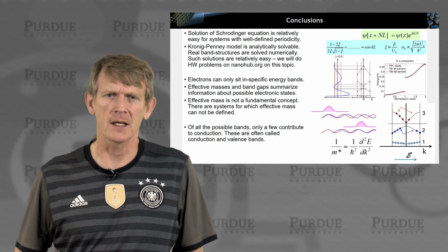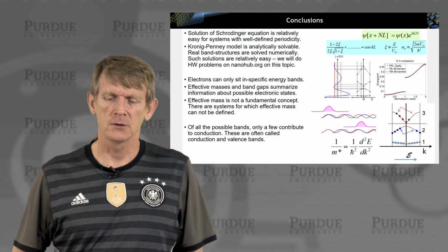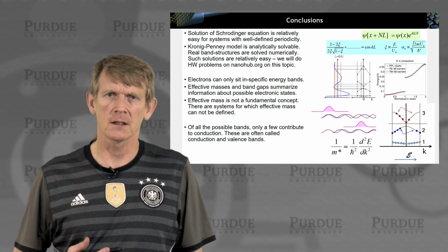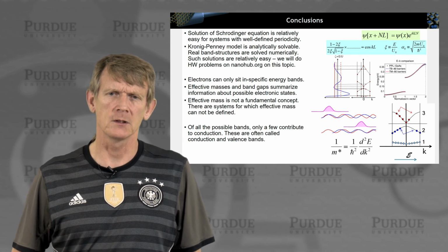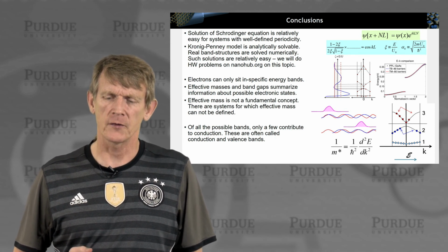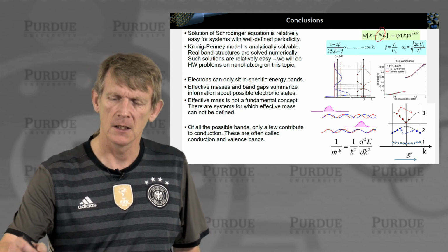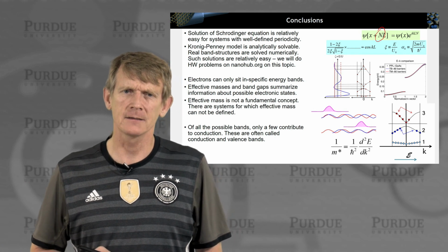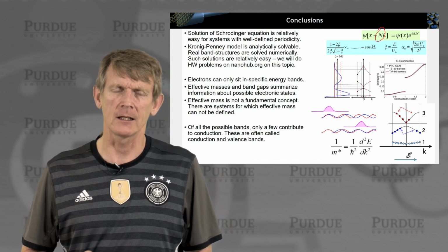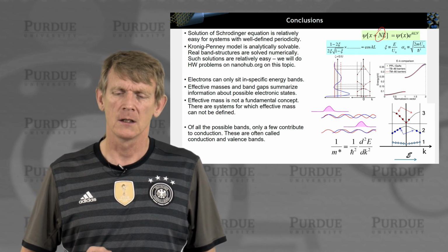Conceptually, they're the same. And in both cases, you depend on introducing a methodology to reduce your infinite system into a finite system. The finite system here on the periodic potential is that you consider a period length of capital N cells, where N is an arbitrarily large number, and it shows up in the discretization of your crystal momentum space.